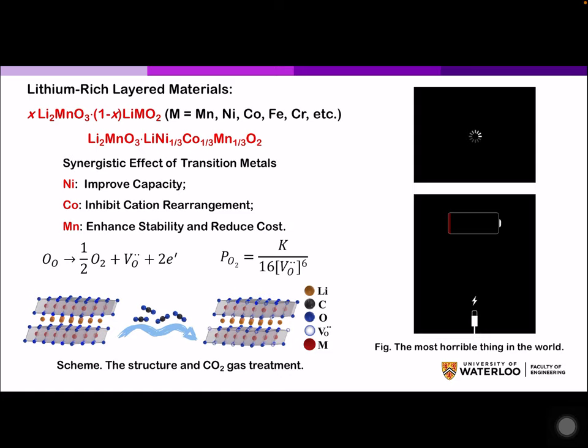Carbon dioxide molecules combine with the oxygen atoms to form a carbonate group, which will be extracted via a simple water wash procedure, then forming oxygen vacancies.